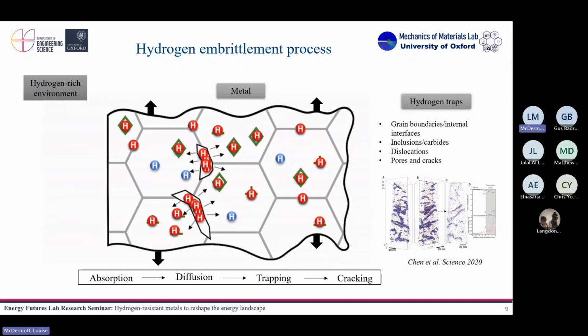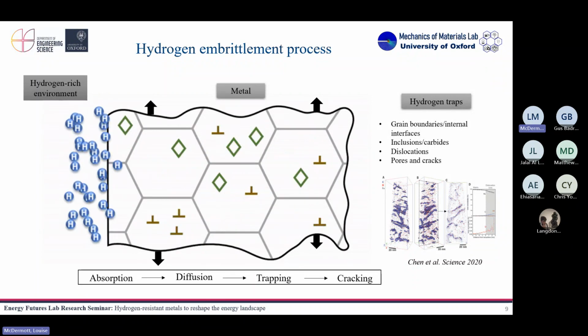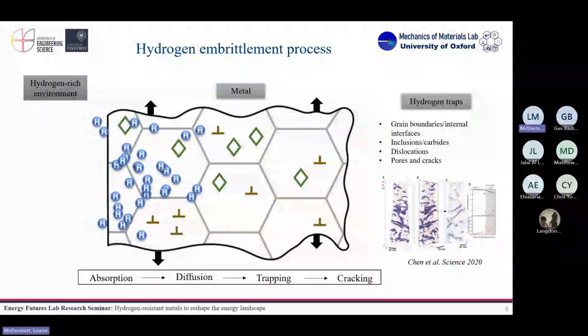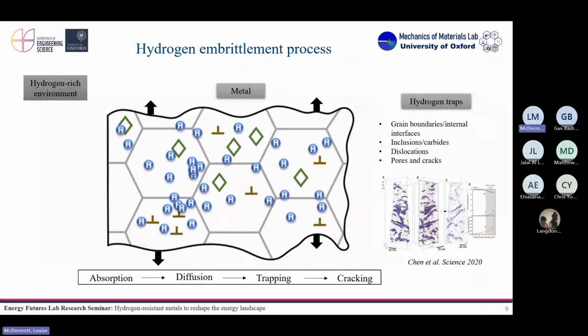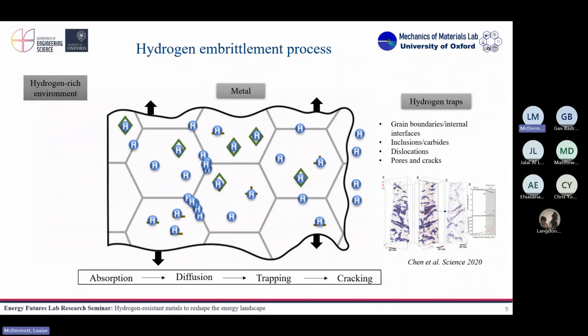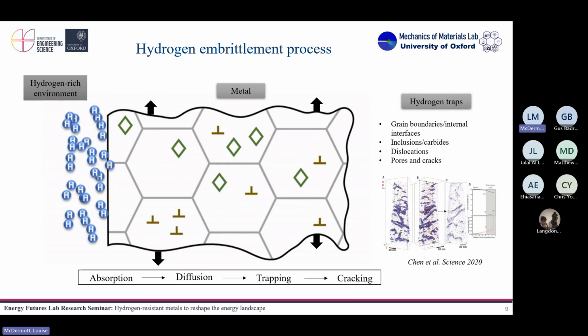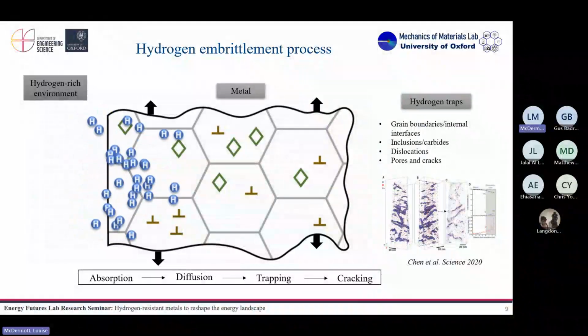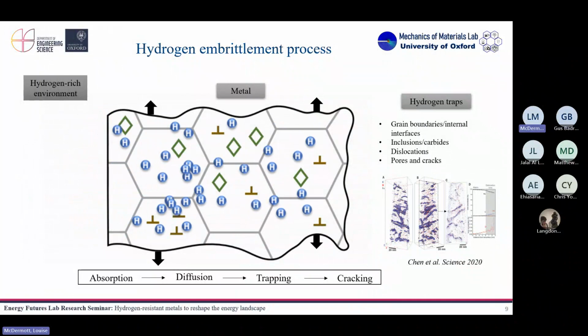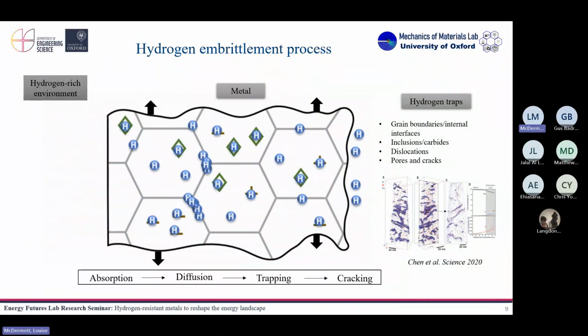Defects can be grain boundaries, any other internal interface, inclusions, carbides, dislocations, pores, cracks. So hydrogen, during that diffusion, is going to be accumulated there. And when in those defects you reach, let's say, a critical hydrogen concentration, and you have a load, remember, that's important, then that's going to provoke cracking. That cracking is going to happen earlier than if you didn't have any hydrogen in your material. So that's the process of hydrogen embrittlement.